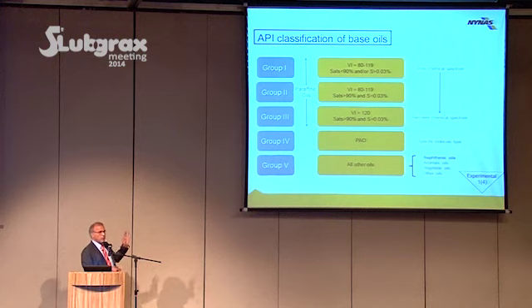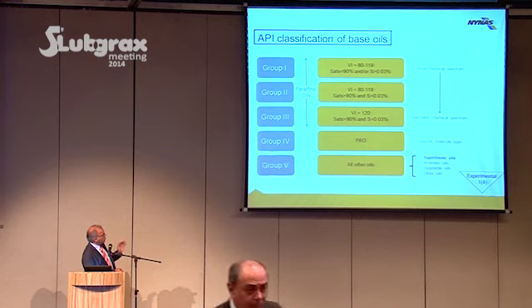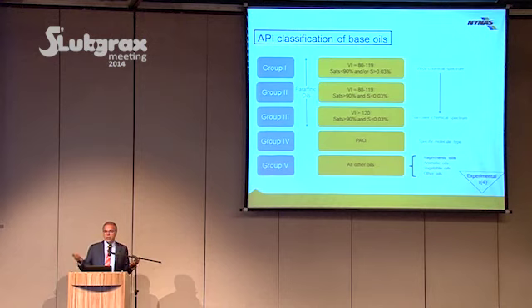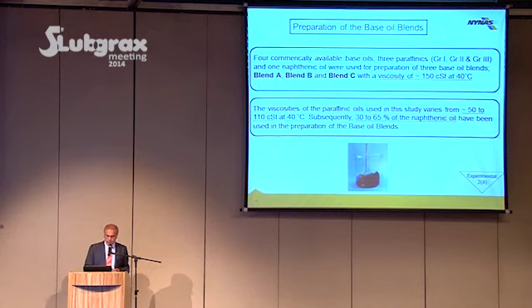But they have excellent oxidation stability. When it comes to naphthenic oils, and all other oils which do not have anything in common, they have been dumped in a box called Group 5. This is what we did. As I mentioned, we prepared 3 blends, viscosity 150 centistokes, and then, of course, we used different amounts of naphthenic oils. The reason is that the starting point for the viscosities of these 3 paraffinic oils was from about 50 to 110.